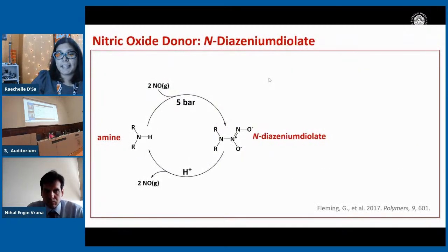Because nitric oxide is a gas, it is actually quite difficult to deliver, and this limits its clinical utility. Therefore, there's been lots of research around being able to form nitric oxide donors that can effectively deliver this drug to the site of the infection. Within our lab specifically, we work with this molecule called N-diazeniumdiolates, which form when you have a secondary amine nucleophile that couples with a nitric oxide dimer to form this N-diazeniumdiolate.